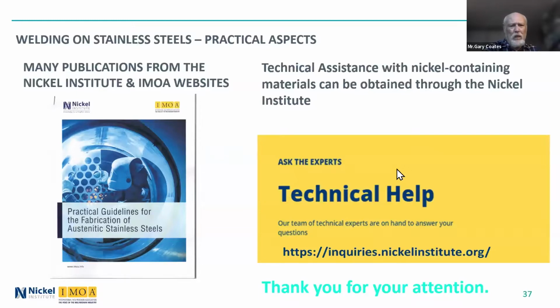So, ferrite number on weld properties. Well, the ferrite doesn't really change the strength level a lot. It does make it a little bit stronger to have a little bit of ferrite there, but it's a relatively marginal effect. Even a 100% austenitic weld with zero ferrite will generally be stronger than the minimum required for the base metal. So the properties are where you have to be careful, where it's detrimental, which again is certain corrosion environments and also high temperature applications.